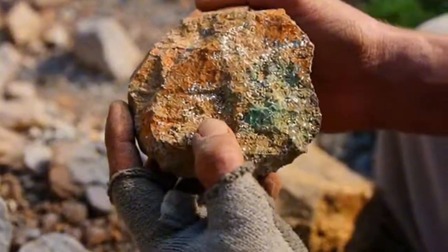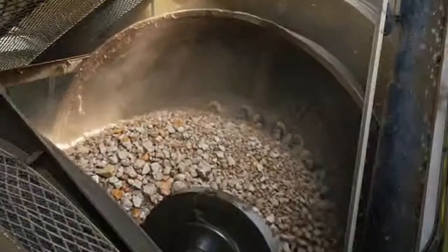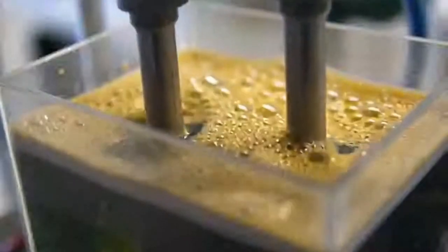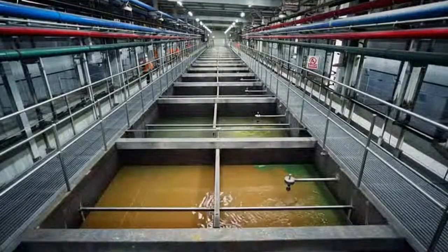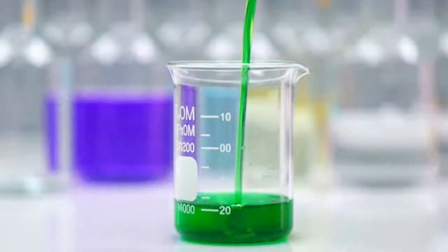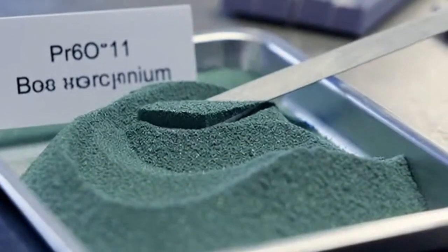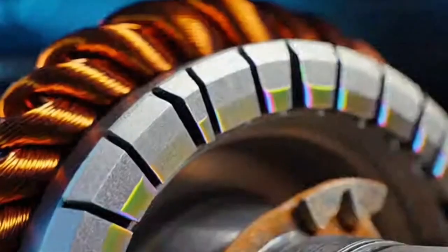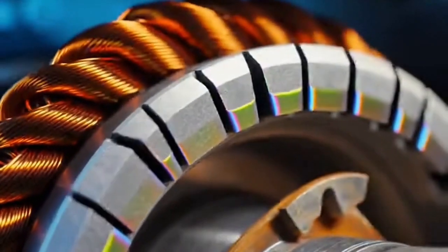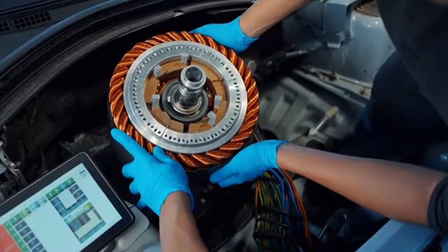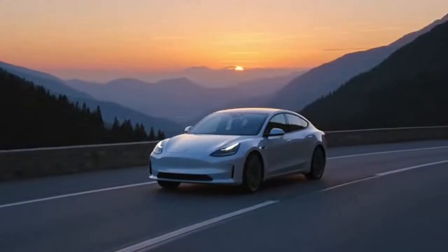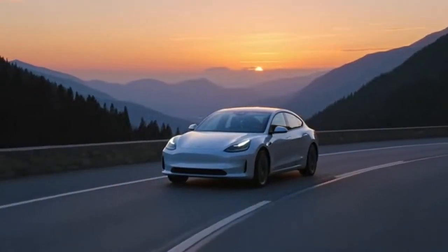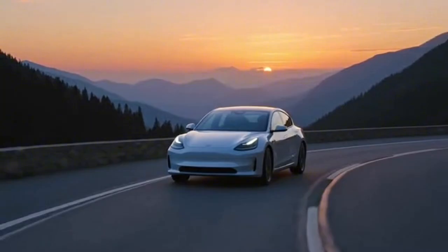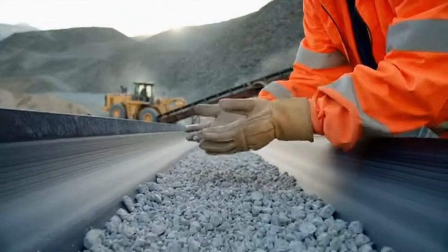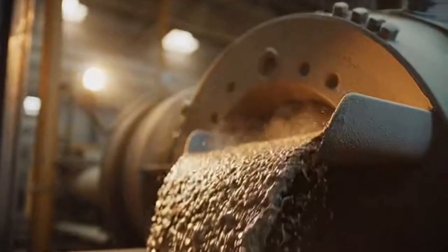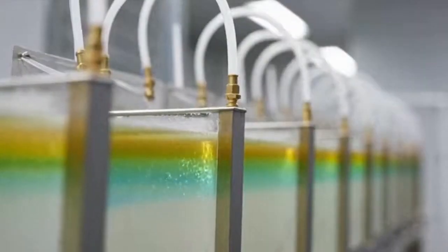Chemical processing to move the rare earths into solution is chemistry that refuses to be rushed. If you are roasting, you must balance temperature high enough to decompose carbonates without wrecking the rare earth phase. If you are acid baking, you must balance acid strength and time against silica gel formation that will make filtration a nightmare. In solvent extraction, the organic reagents age and degrade, crud forms at the interface, the mixer settlers need maintenance, and the control room is basically a pH vigil.